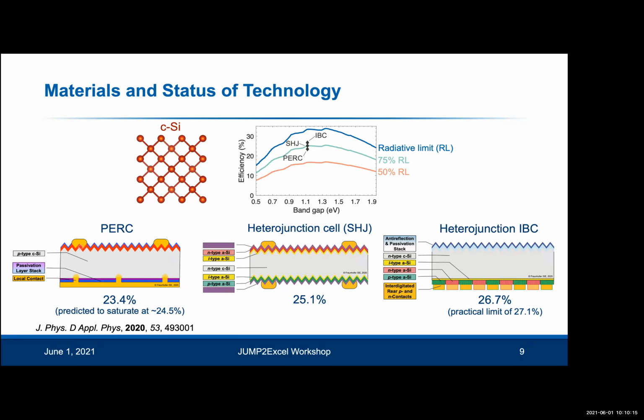The front surface is called the emitter, where you have a homojunction between P and N-type silicon. You can see that the entire surface is covered with this blue passivation and anti-reflection coating, apart from the small areas where you have metal contacts. And the rear is also passivated. For example, what's commonly used is alumina, which is grown by plasma enhanced CVD or by ALD.